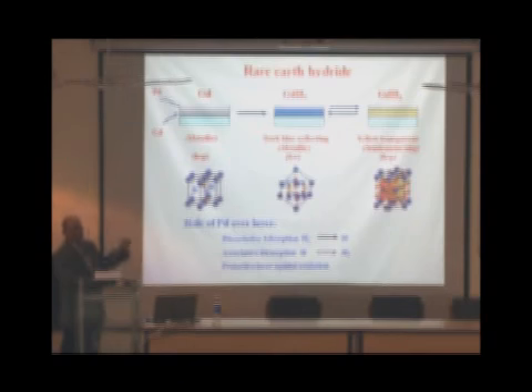You can use the change in electrical properties, or you can use the change in optical properties. Why is palladium required? Because it's not the molecule of hydrogen which interacts with the rare earth material, it is the atomic hydrogen which interacts and reacts with the material as we go in this direction or when we come back in this direction. So the role of palladium is that palladium converts the molecule of hydrogen into atomic hydrogen, both when hydrogen is going in, and also when the hydrogen is coming out, in the reverse direction.